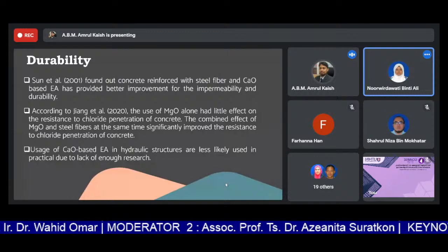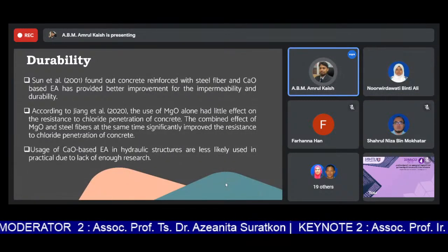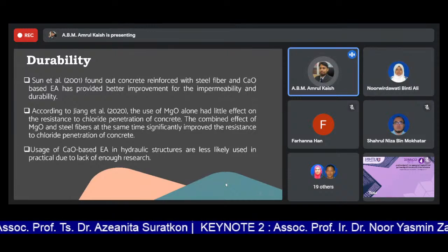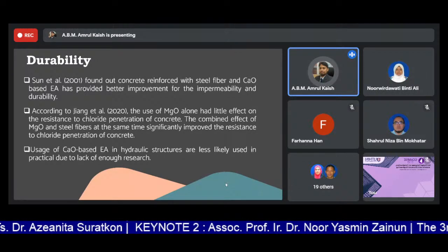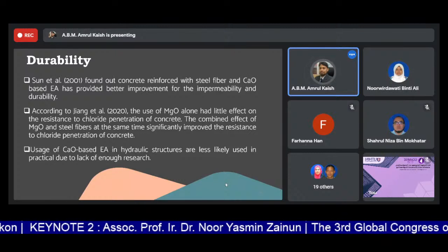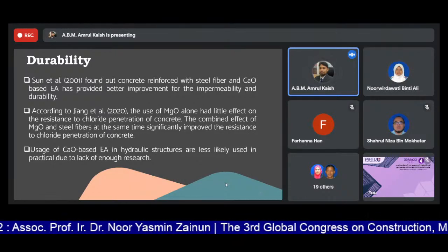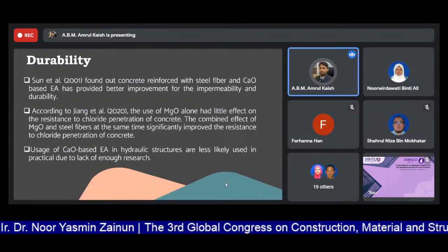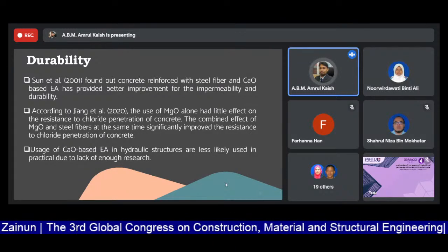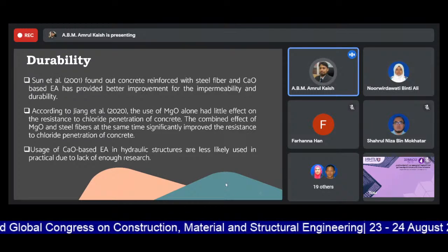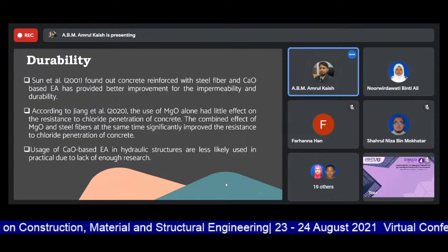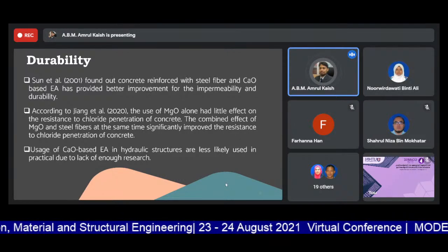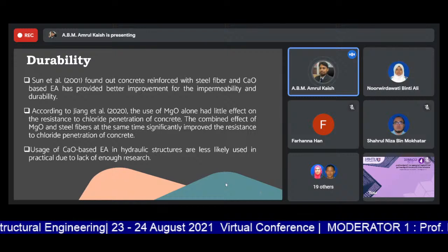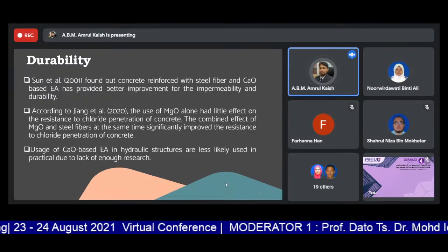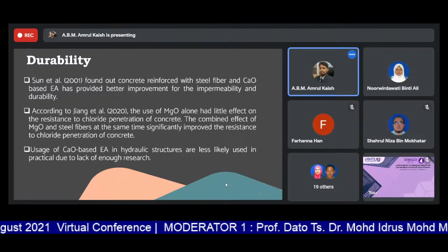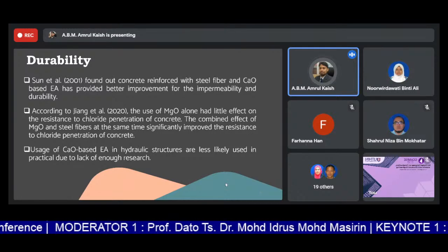Okay. Thank you for this question. Basically, the effect of fiber is different from the effect of other additives. Fiber normally does not significantly affect the durability. However, additives significantly improve the durability. So what happened in this study was that magnesium oxide causes a little expansion that reduces the porosity of the concrete, and this is why the durability is affected, not because of the steel fiber.